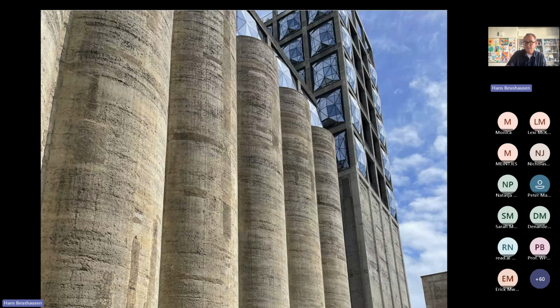And typically, if you have a structure that is as old as this one, I believe it's about 100 years old, that shows so much reinforcement corrosion damage, then even after patch repair, you would expect to come back every 5 years and do more and more patch repairs at regular intervals. And I expected this to happen here also. And this is a recent photograph, and you see very few new delaminations, and there was no further spalling. There's hardly any steel exposed. And the reason for the great performance of this particular structure after repair is that they applied a hydrophobic sealant, which keeps out the moisture, the water.